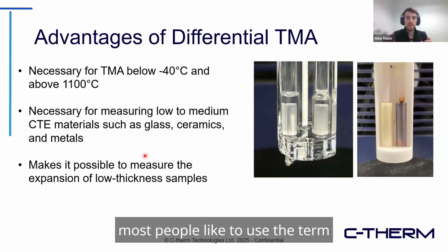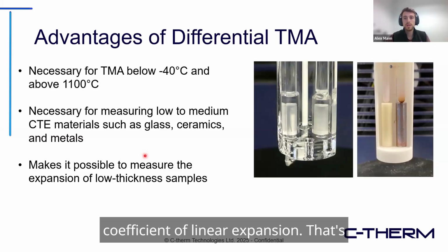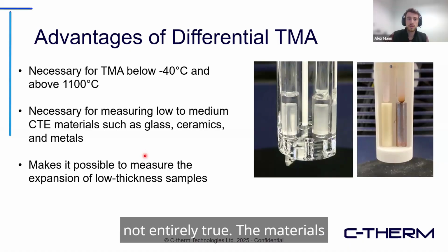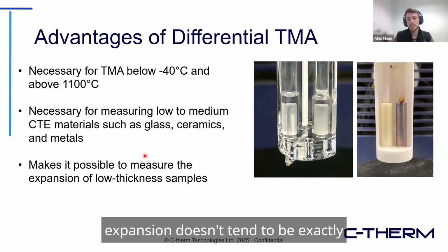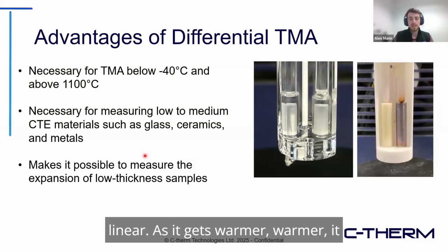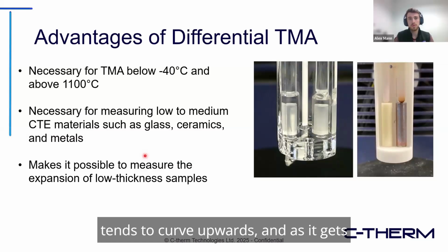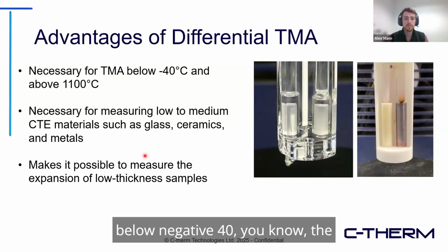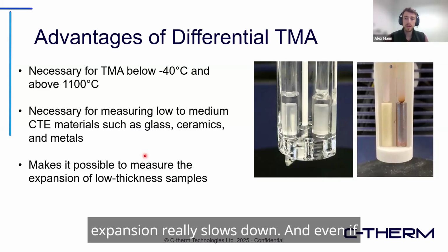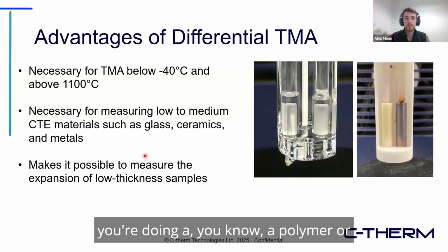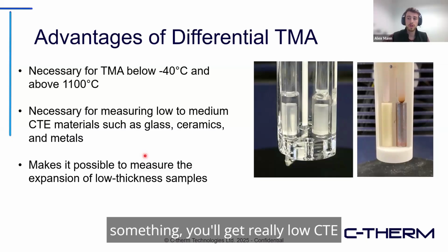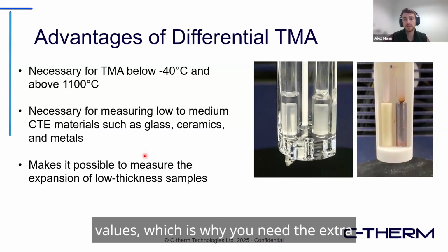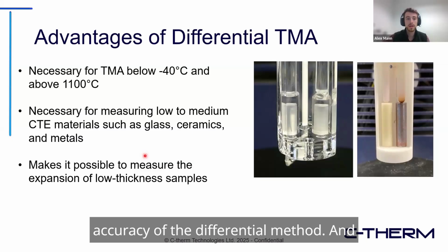So most people like to use the term coefficient of linear expansion. That's not entirely true. The material's expansion doesn't tend to be exactly linear. As it gets warmer, it tends to curve upwards. And as it gets colder and colder, it tends to curve a little bit downwards. So once we get below -40, the expansion really slows down. And even if you're doing a polymer or something, you'll get really low CTE values, which is why you need the extra accuracy of the differential method.